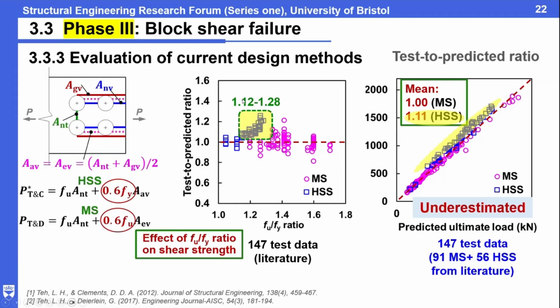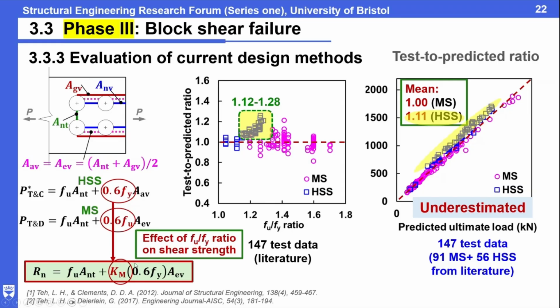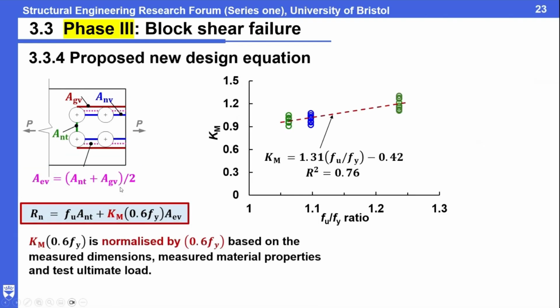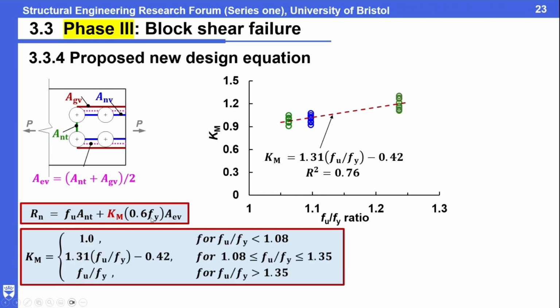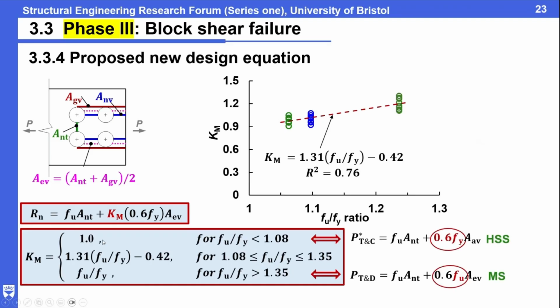And then how to account for this factor from the strength ratio. This is another work we did. We want to introduce a factor to account for this kind of effect from the strength ratio. But how to qualify this factor? From our test data, we fit an expression for this Km directly. And then if we do it like this, our design equation will be expanded to a step function. The upper boundary and the lower boundary, you can see, are the same as the literature equation for the high strength steel and mild steel. And we also have the middle one to consider the partial strain hardening of the high strength steel if the ratio is between 1.08 and 1.35. So this is our work in the middle.